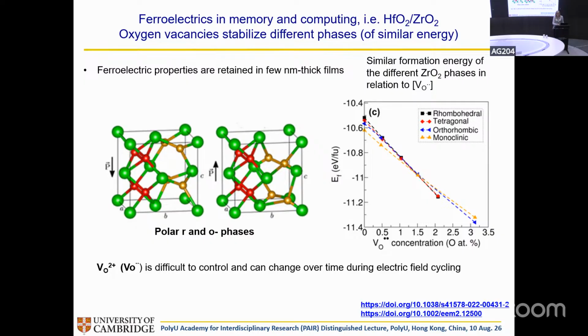But as you see in this right-hand graph here, if you look at the formation energy of different structures, rhombohedral, tetragonal, orthorhombic, monoclinic, they have very similar formation energies relating to the vacancy concentration. So for a vacancy concentration of 1 atomic percent, you can see that the formation energy of all these structures is about the same. So you might be able to fix on the structure in the first place, but once you start applying a voltage and cycling that and switching it, and you're moving the oxygen around, you can change the oxygen content a little bit, and then you're going to change the phase.